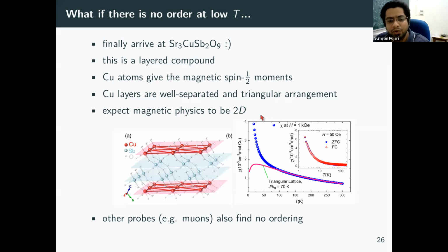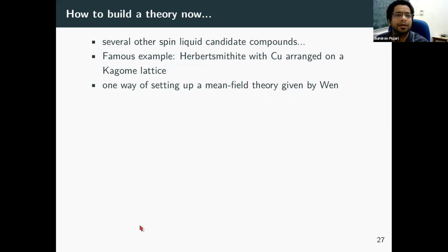And it turns out if you look at susceptibility, which is shown here, you can just focus on these big blue dots in the main panel. It looks as if the Curie paramagnetic behavior just keeps going on. There is no sign of a phase transition to an ordered state till the lowest temperature that the experiments were done. So what's going on? Because we know at low temperature the spins are going to interact. So why is ordering not found? And there are other experimental indications of no ordering.